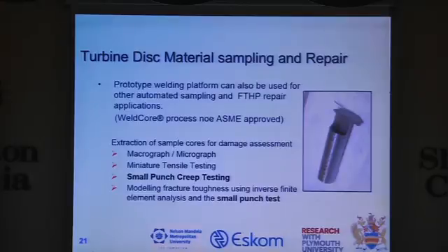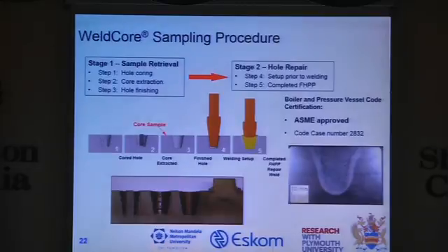But by taking that out and getting that history, I need to repair the hole, and that's what this is about. So what can we get from that? We can get macro and microstructural information. We can get tensile, static strength information. We do a lot of small punch creep testing currently for industry, because we do that on an 8 millimeter disc, half a millimeter thick, that we cut out of this at different places. We do a lot of fracture toughness using inverse finite element analysis and the small punch test. That's just another hour talk for another day.